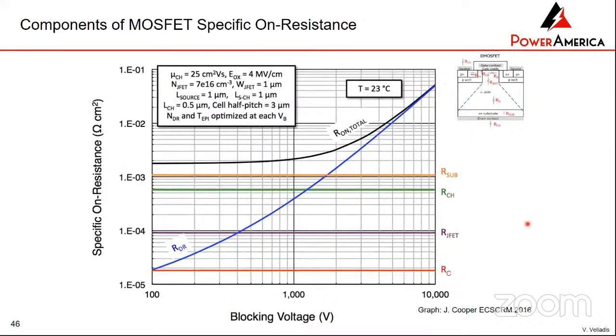So if you look at the total resistance, you can see that if you're below maybe 2000 volts, right? The contribution of the substrate and the channel play a role. But by the time you get above 2000 volts, and if you look at 10,000 volts, for example, the total resistance from the device comes pretty much from the thickness of this thick drift layer. So depending on whether you're making a 1000 volt device, 2000 volt device, 6000 or 10,000 volt device, these are the resistive elements, and that tells you what you need to optimize.